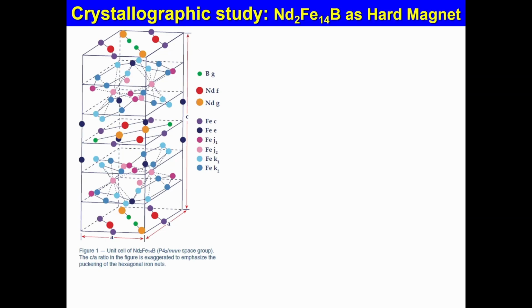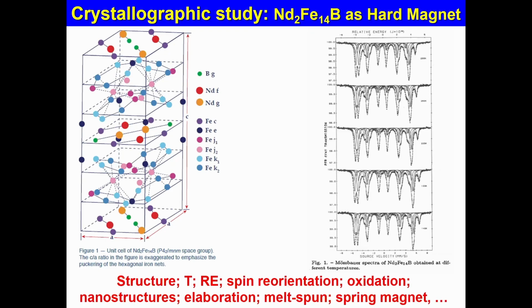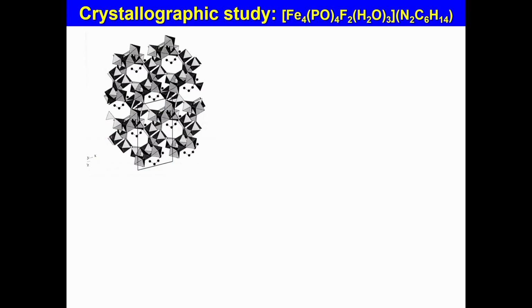But at the beginning, with the first pure neodymium-2 iron 14 boron, it was difficult to identify because all spectra are there versus temperature. So, of course, it took time to fit the spectra and to attribute to each sextet a well-established site. And as I was telling you yesterday, you see that your spectra are much broader. So that means you are highly sensitive to the symmetry.